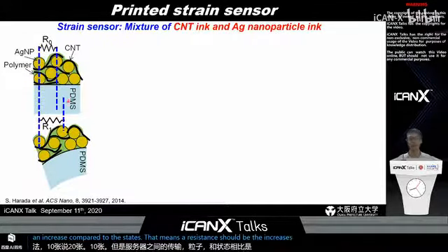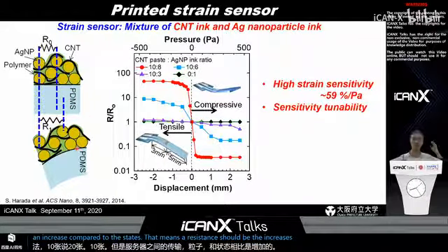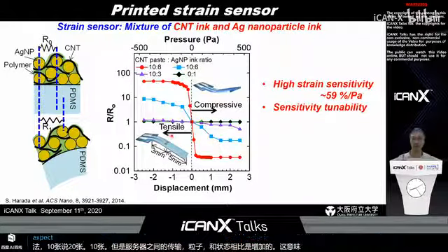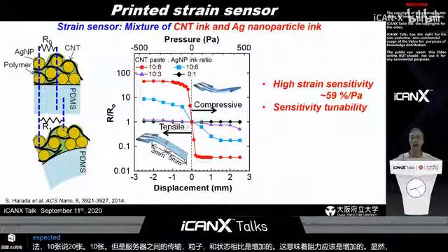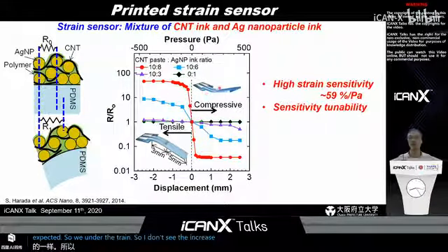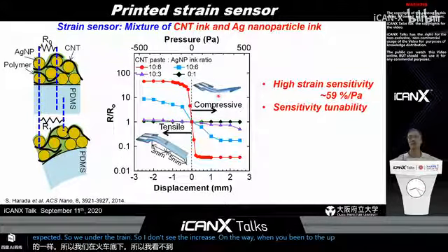So this is the experimental result. As we expected, under the tensile strain the resistance is increased. And also when we bend to the upward side, the film has a compressive strain.